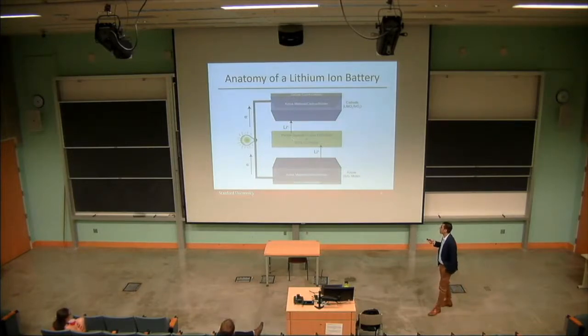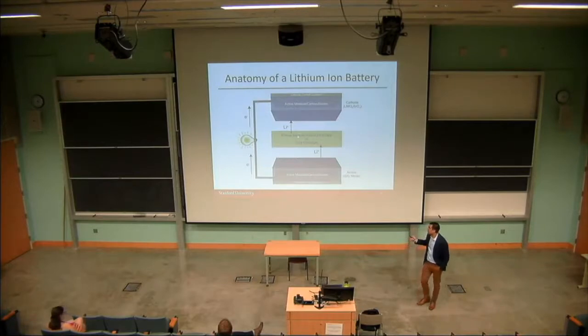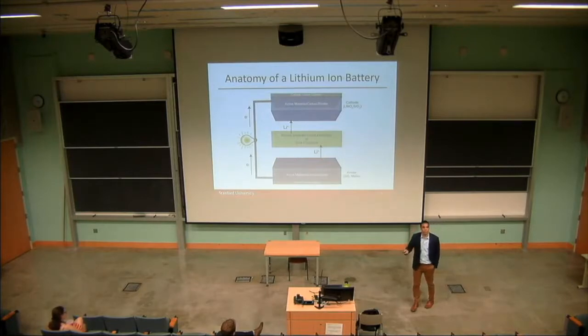Then you have your separator, so this is either some sort of porous inert material that you fill with a liquid electrolyte or a solid lithium ion conductor. And this is really the key to making the battery work. This is an ion conductor, but it's electronically insulating, and so when you have high energy electrons and lithium ions here, they want to go to your cathode during discharge, but because the electrons can't move through this separator, they're forced to go through the external circuit, and that's where you get the work.